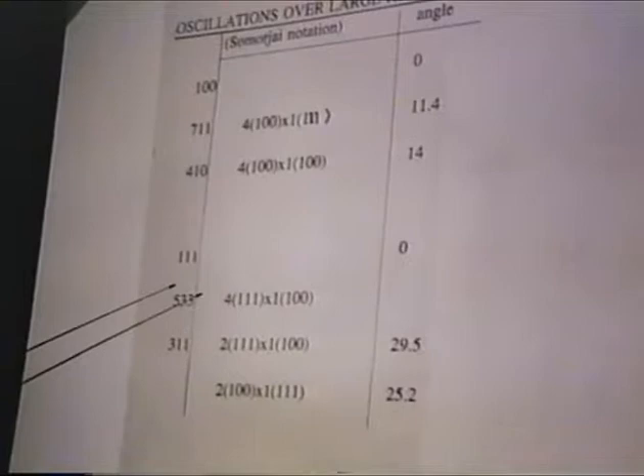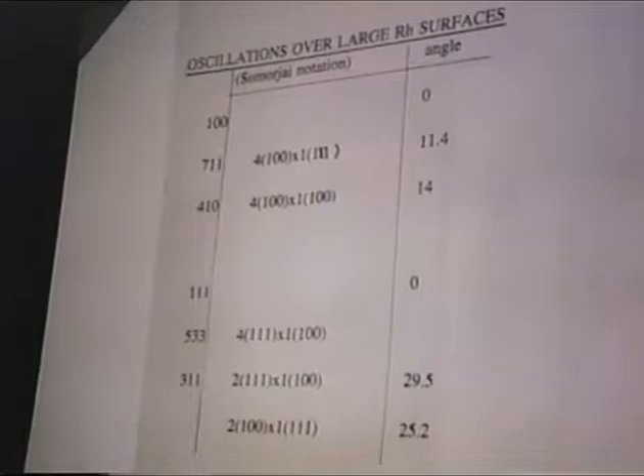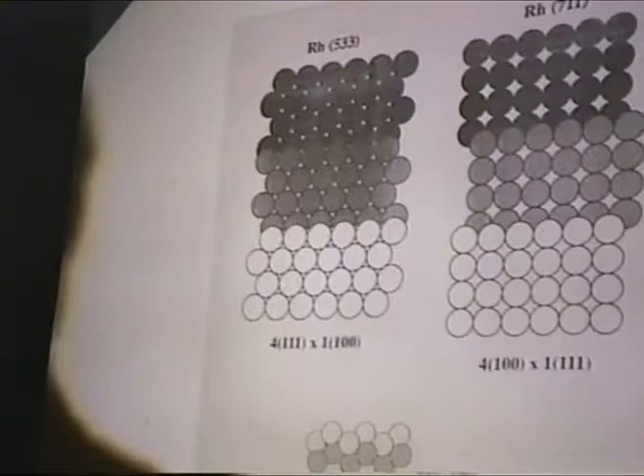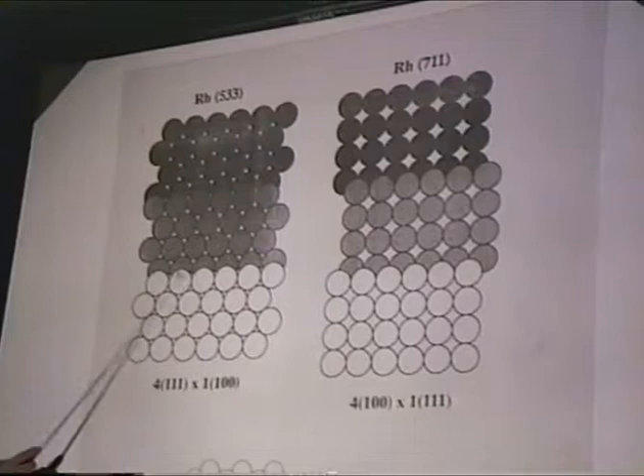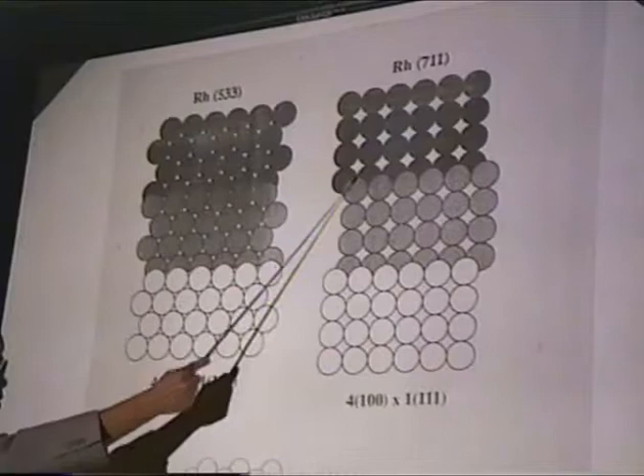For rhodium, it is very different. For rhodium surfaces, we studied six different surfaces, and the selection of these single-crystal surfaces was based on work done with the field ion microscope. It turns out that you need suitable terraces on the surface to obtain oscillations — we did not find oscillations on surfaces with Rh(100) terraces. For example, you have oscillations on the 533 surface, which has Rh(111) terraces with Rh(100) steps, but you don't find oscillations on 711, the surface with Rh(100) terraces.